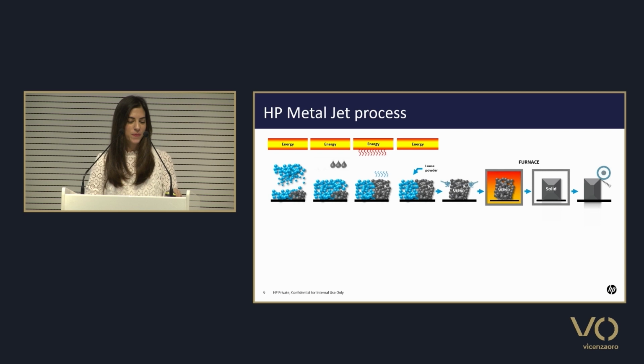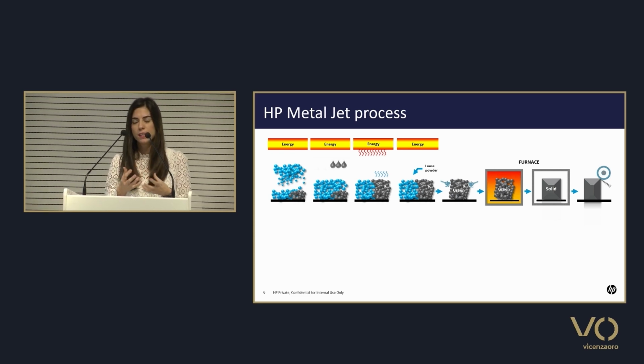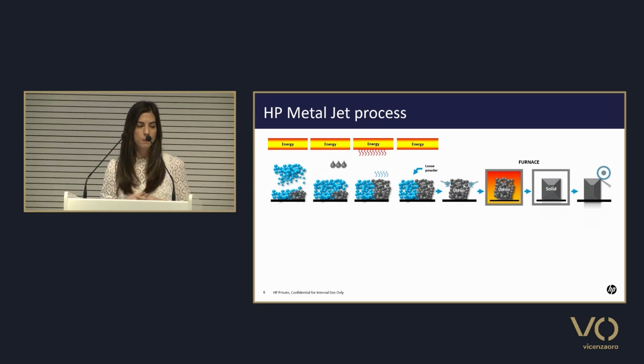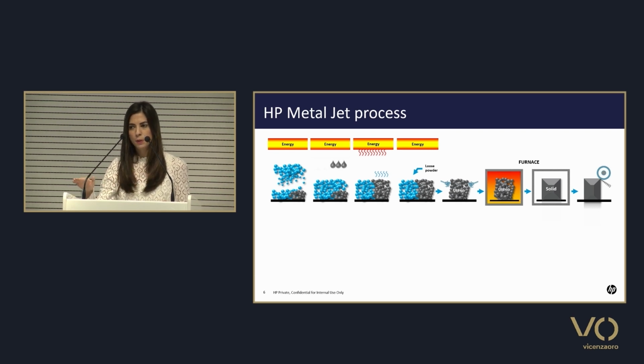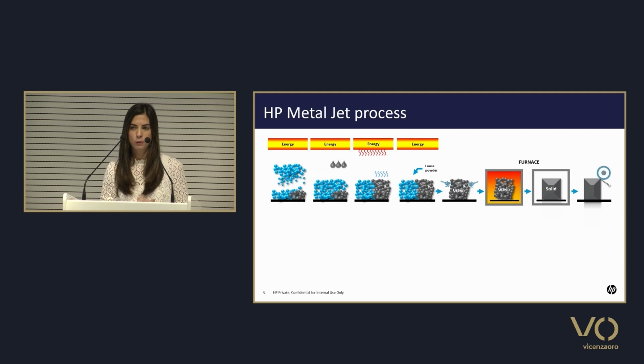Okay, here we go. So what is the process itself? Here we say HP MetalJet, but it's quite generic to BinderJet in general. We start by spreading a layer of very thin metal powder over the build platform in the printer. And then we come with print heads, very similar to the ones you have in your printers at home, that put ink exactly where you want to print the part. It's a surface-based process, so with one pass of the print heads, you are printing the full area that you want to print.